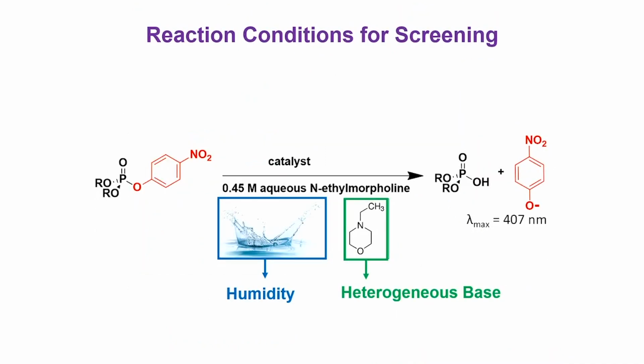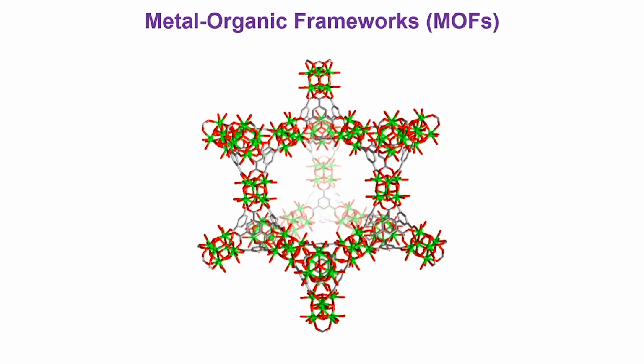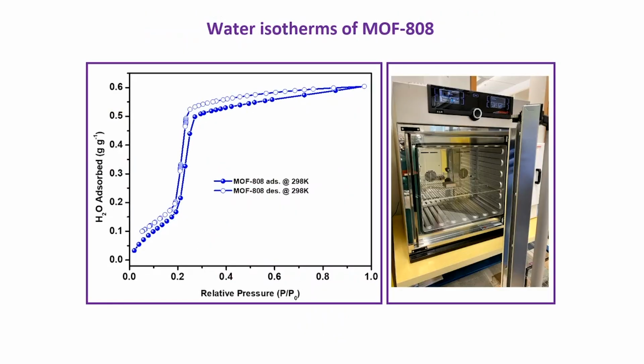Okay, that's good. The second thing, how can we now rely on humidity? Let's go to the last MOF I talked about that has really fast reactivity. If you do a water isotherm of that particular MOF, you'll find that anywhere above 20% relative humidity, there is a huge, sharp uptake, and that's really nothing but the filling of these cavities. That means anywhere above 20%, the cavities of this MOF are full. My gut feeling, this room is about 50 to 55% relative humidity. If I put that MOF right here, in no time it will suck up water from the air, and the cavities will be full.